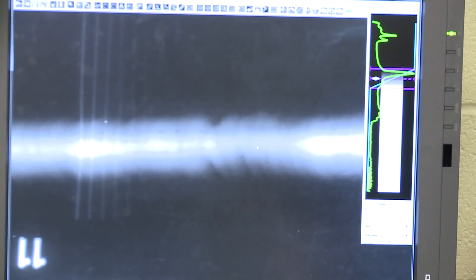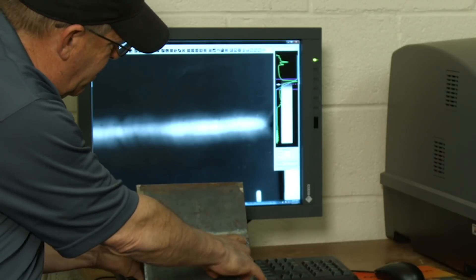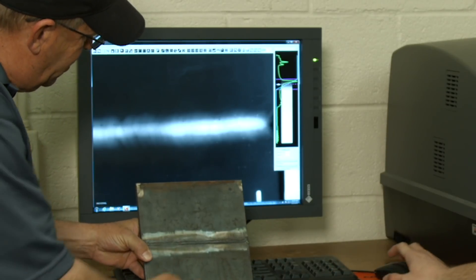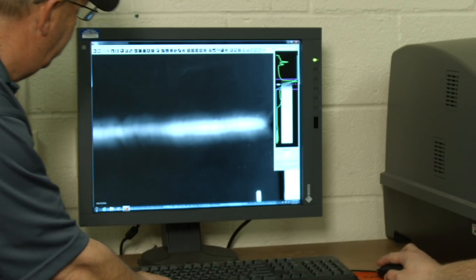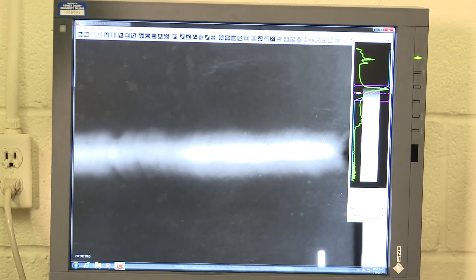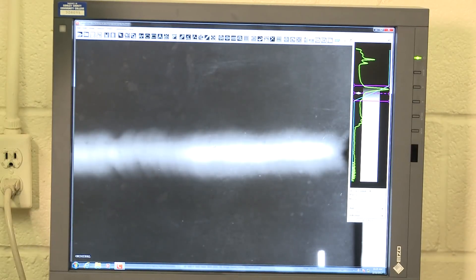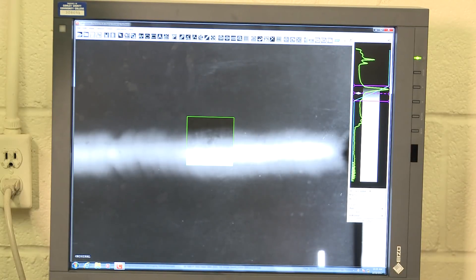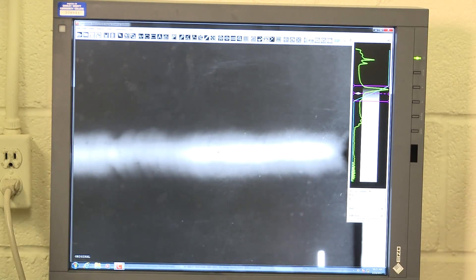If I blow this up just a little bit for identifier purposes, this very light area on the right-hand side shows us a root area or cap area that's relatively thicker than the rest. You can see the root's just a little bit thicker. Beyond that, we have some discontinuities or possibly inclusions that lay in the middle of that weld, kind of towards the far side of the root. You can see that darker image appearing right in the center of the box — that's a good way to tell density-wise on the film what a discontinuity would look like.